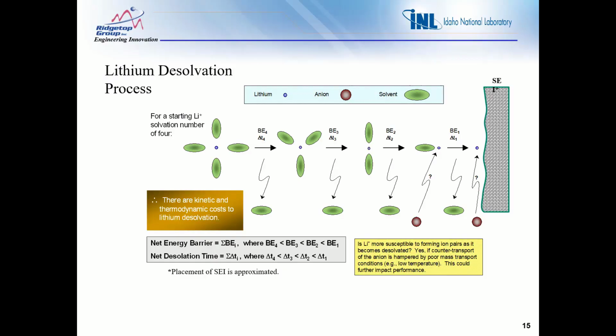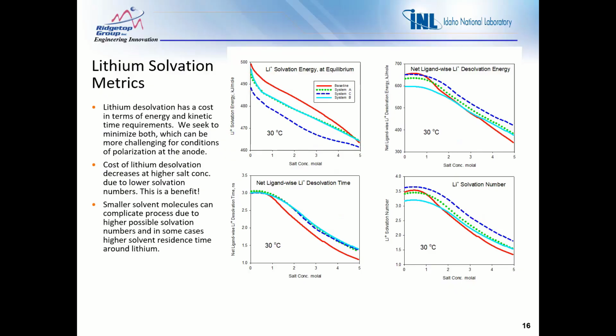As we march to the right and shed each solvator, there's a binding energy and a delta T that's associated with that. So there's a kinetic analysis of this process as well as thermodynamic. If you sum up all of the delta binding energies and delta times, you get your costs for the lithium desolvating, which is a good selection criteria for different electrolytes. You'd like to minimize that to reduce the energetic requirement for preparing the lithium to enter the host.